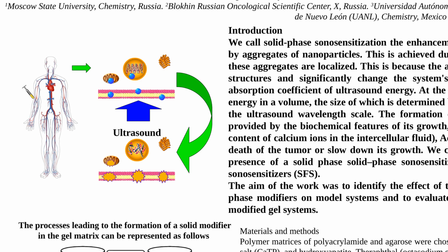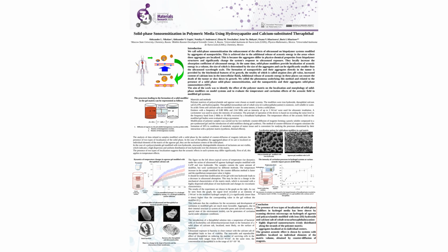phase sonosensitizers. The aim of this work was to determine how the polymer matrix affects the localization and morphology of solid phase modifiers in model systems, and to evaluate the temperature and cavitation effects of the acoustic field in modified gel systems. For the model systems, we use polyacrylamide and agarose polymer matrices. The modifiers were iron hydroxide, the calcium salt of theraphthol, and hydroxyapatite.